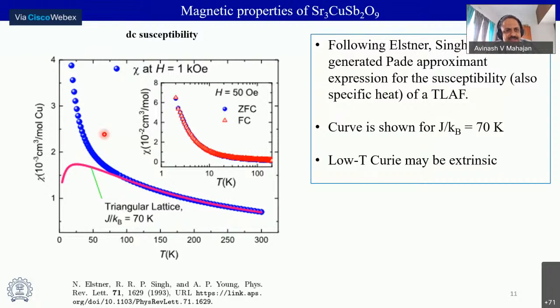The discrepancy at lower temperatures is not abnormal. One often has orphan spins in these systems, and at low temperature, because of the 1/T Curie behavior, they really overwhelm the data. And so one could still have a triangular lattice behavior, and maybe at lower temperatures, other interactions or parasitic spins or some other features come in. So this is the situation up to now: there is no sign of ordering. There's a suggestion of triangular lattice antiferromagnet interactions being present.